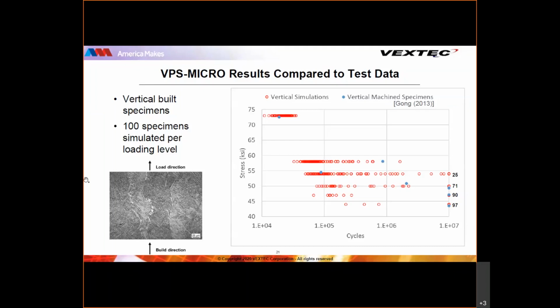50 KSI, and capturing that mechanism, especially by looking at the fracture surfaces. And noting from the fracture surfaces, we have to do some testing and see did that mechanism switch over. And in this case it wasn't, but you can start to get internal cracking, especially at the very low stresses. And these are mechanistic models, so you have to explicitly put that mechanism in. Now you can put it in and run it, and if it doesn't fail, well, that's fine. But you do have to understand mechanistically what's going on, and changes in the mechanism, especially internal versus external, transgranular versus voids, and at what stresses those happen. The model should be able to capture that, but you still have to make sure that you've got them as one of the allowable failure mechanisms.